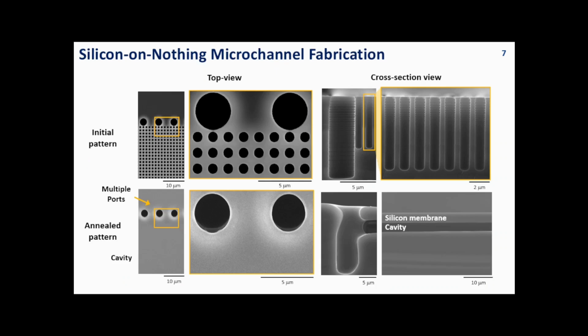To inject liquid into the microchannel, we positioned a larger 4 micrometer hole array around the smaller 1 micrometer hole array, which forms the silicon-on-nothing structure through surface diffusion. During high temperature annealing, the smaller holes form the channels, while the larger holes remain open because their surface diffusion rate is much slower, preventing the surface from closing. In our previous work, we optimized the diameter and spacing of these larger holes to ensure proper coupling. Since the microchannel is connected to the larger holes, they can be used as the fluid inlet and outlet.